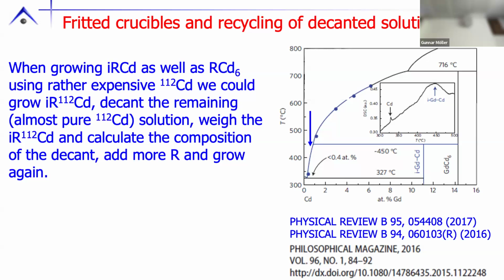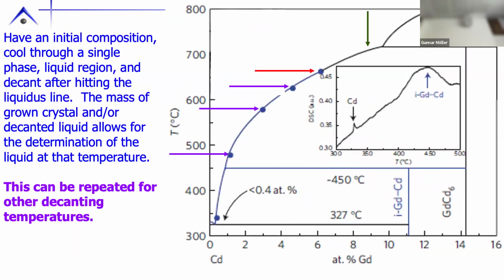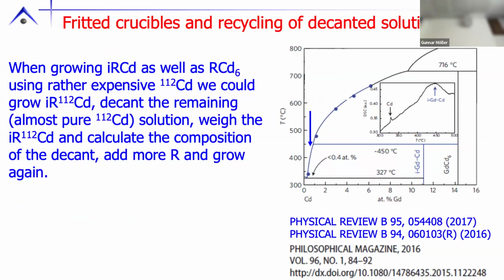Okay, fine. So for these materials, cadmium is quite an absorber, so we have to use cadmium-112, which is an isotope that you buy by the milligram. Very expensive. By the milligram. I was doing this with Alan Goldman. We wanted to look not at the gadolinium, but the terbium. If you come in here, you're basically 99% cadmium. You grow a little of this, you throw all that cadmium out. That's bad. With these fritted crucibles, you're keeping your decant clean. In the old days, you decant into silica or fiberfrax, and it's just a mess and you contaminate it. Now you can keep it clean.